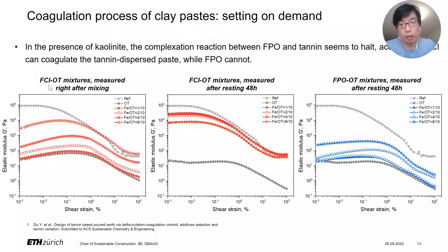Same like before, we also did some oscillation test. On the left is the paste right after mixing. The measurement was done right after the mixing. So as we can see at the beginning, even though we put iron citrate in the mixture, the rheological behavior is quite similar to the pure tannin. So it's quite liquid at the beginning, but with the time going, we see the curve slowly moving toward the reference one. So that means they are not liquid anymore. They are rigid, and this dispersing effect of the tannin has been removed by the citrate one.